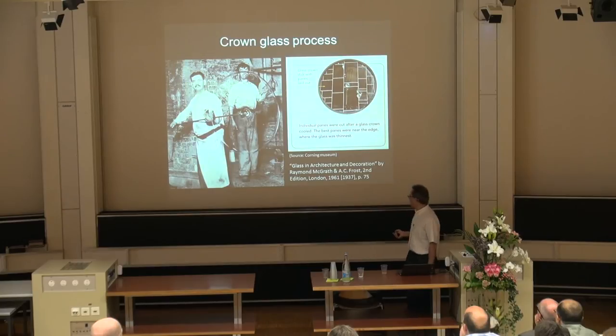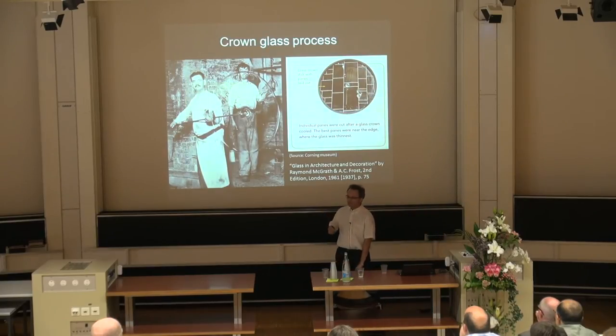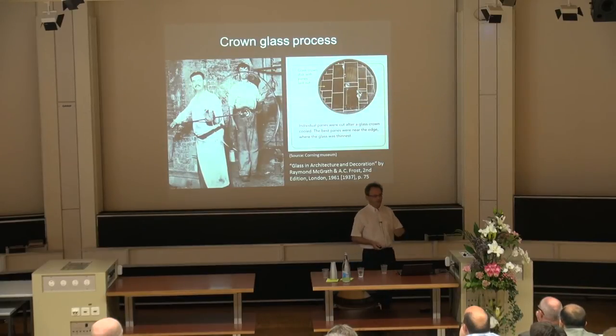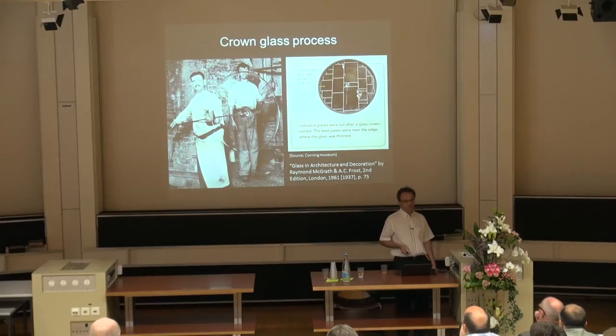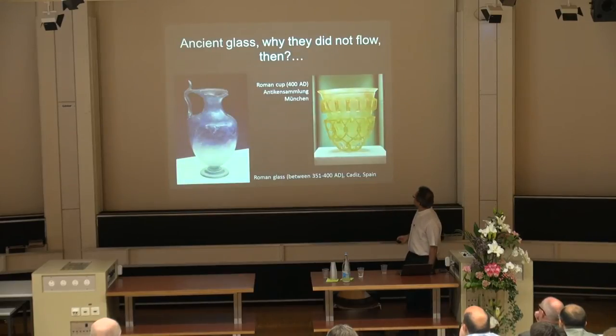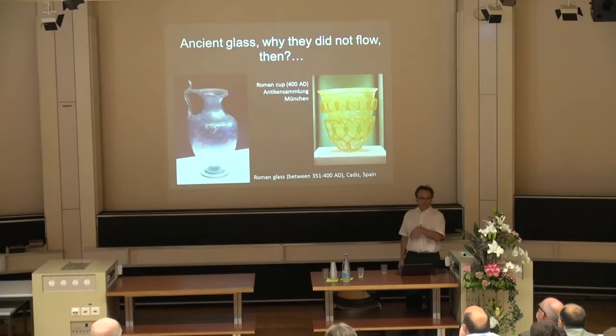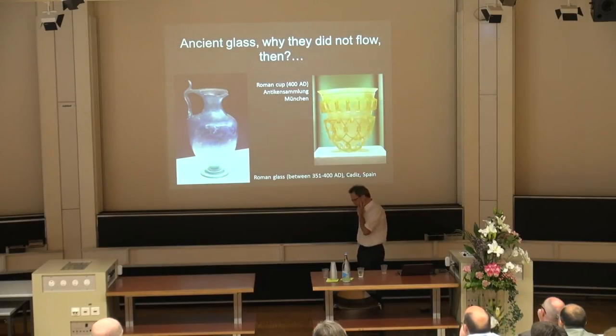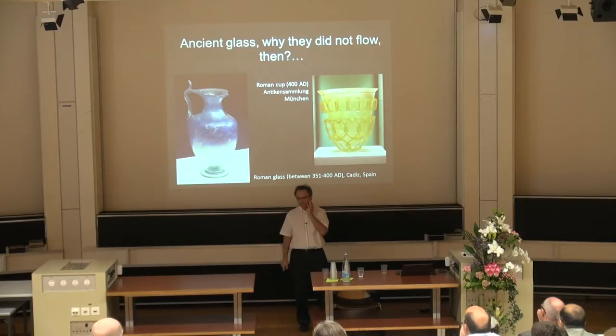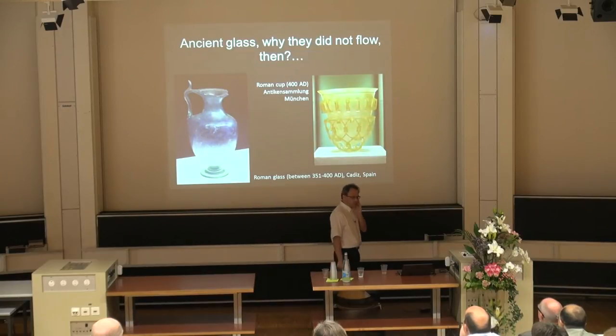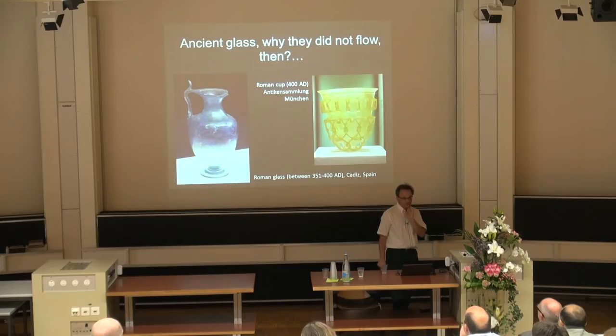So what's most likely the reason why the cathedral glass is like that is because when they were mounting it, they were always putting the thicker edge on the bottom. It's just pure logic, okay? Now, if you are still not convinced, without even thinking of the physics, it's amazing because glass is at the same time one of the materials we understand the least, and at the same time, one of the materials we have known about for a really long, long, long time.